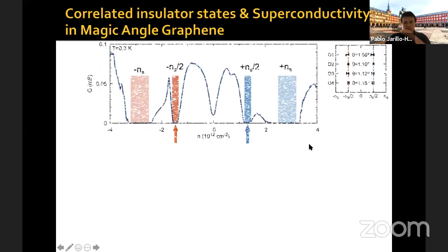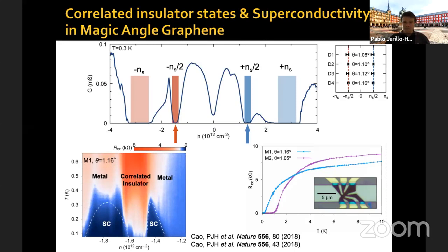In particular, what we discovered a couple of years ago is that when you put an integer number of electrons, in particular 2 electrons per moiré unit cell, out of a maximum of 4 electrons or 4 holes per moiré unit cell that you can put in this flat band, which is sometimes called filling factor 2, or maximum superlattice density divided by 2, you have unusual correlated electronic states. These electronic states only happen for angles very close to the magic angle, okay? And then if you dope a little bit away from these correlated insulator states, you have superconducting domes, yeah?